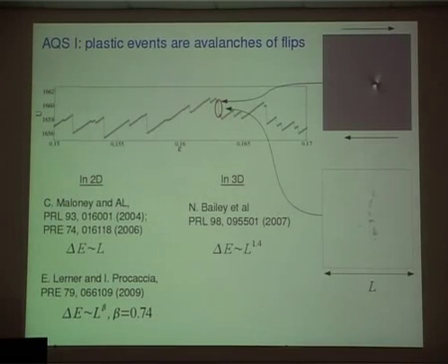But now, if you look at the whole process of these descents, you find that the gray part is my whole system. That's a system with 50,000 particles. The gray tells you when something happens, and you see that you have a cascade. So one plastic event is not one shear transformation, but a cascade of shear transformations.